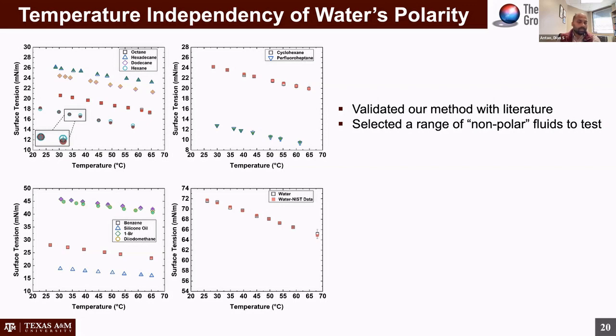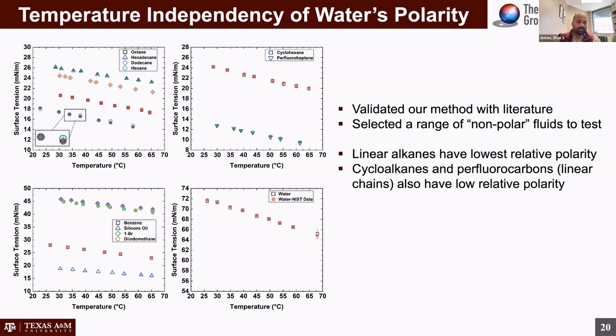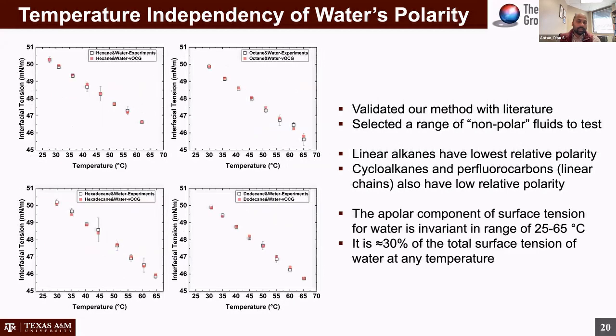We have some conflicting results from that. But what does work well is that because these linear alkanes are known to have really low relative polarity, the model and the experiment match up fairly well within this assumption, with the assumption that the surface tension component for the dispersion component for water is fairly constant over this temperature range between about 20 or 25 and 65 degrees C. And in fact, it is about 30% of the total surface tension of water for these temperatures.